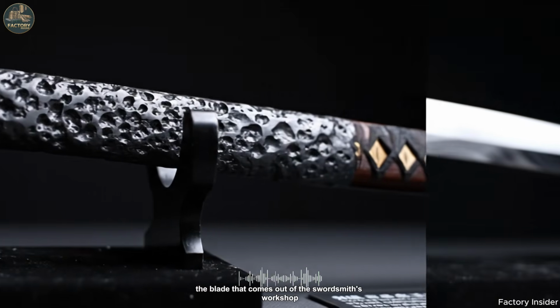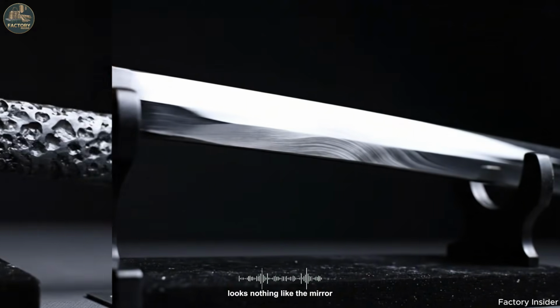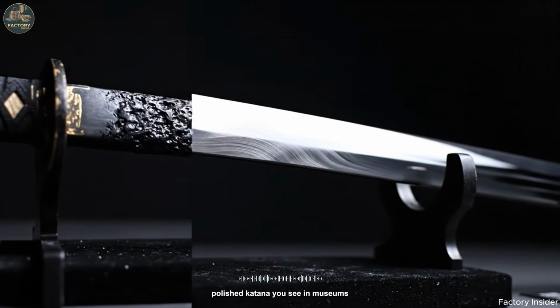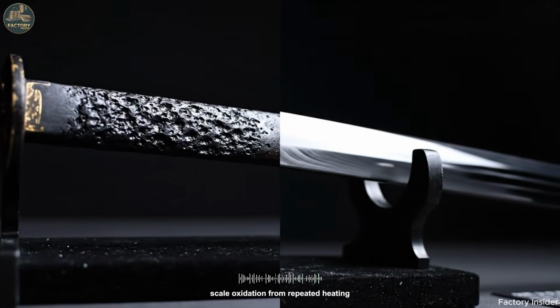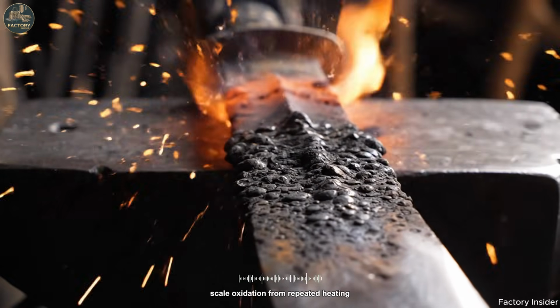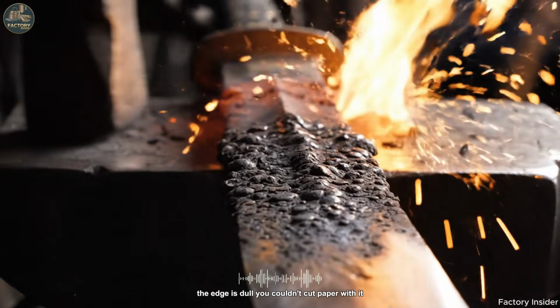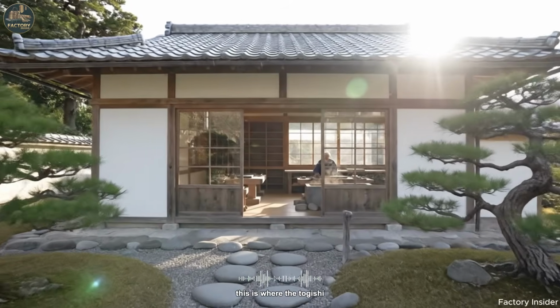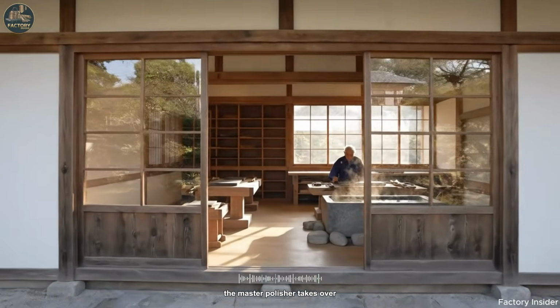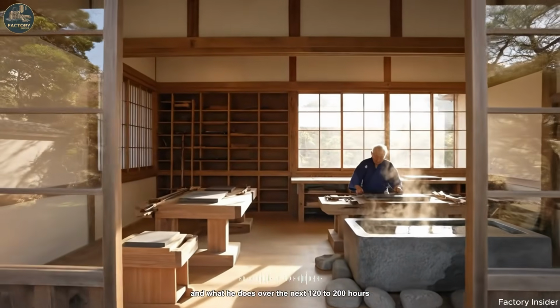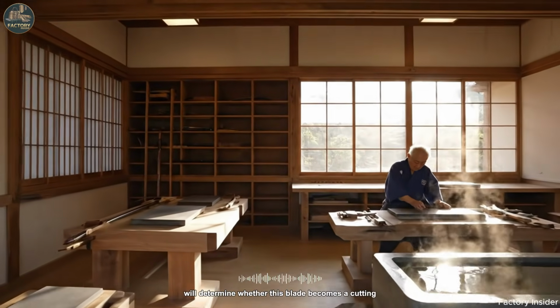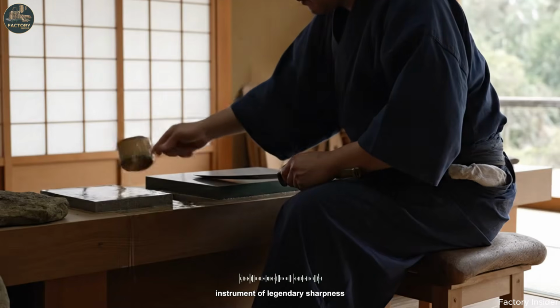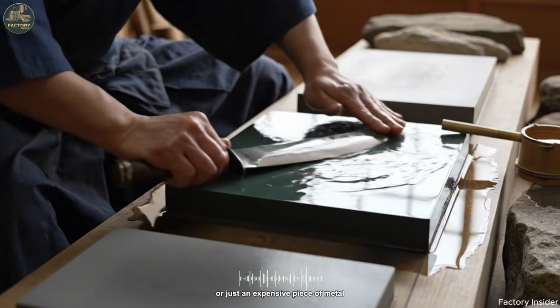The blade that comes out of the swordsmith's workshop looks nothing like the mirror-polished katana you see in museums. It's covered in black scale, oxidation from repeated heating. The edge is dull. You couldn't cut paper with it. This is where the togishi, the master polisher, takes over. And what he does over the next 120 to 200 hours will determine whether this blade becomes a cutting instrument of legendary sharpness or just an expensive piece of metal.